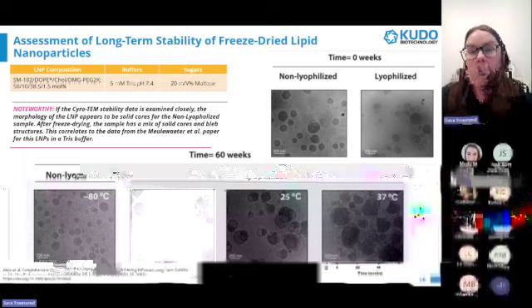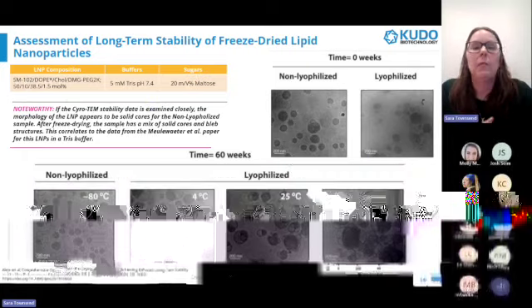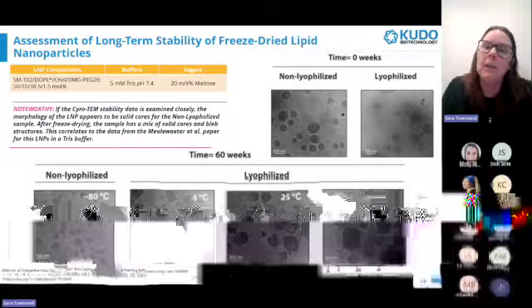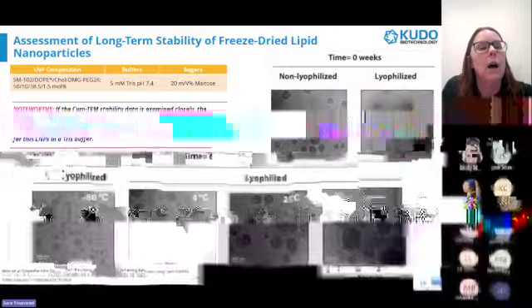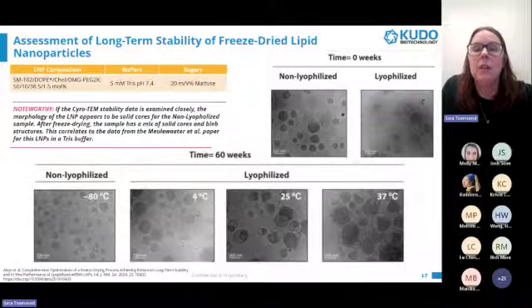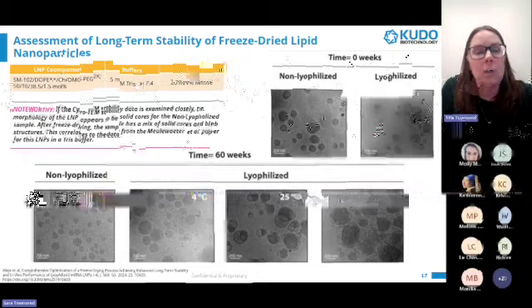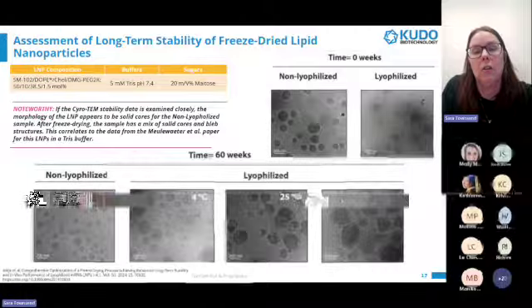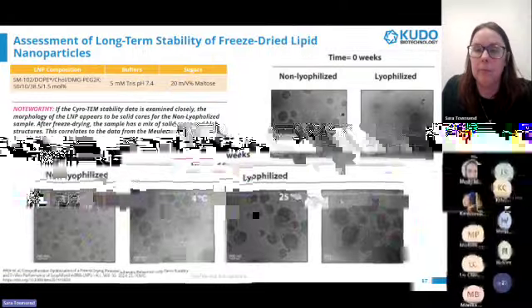Xu et al. also published on cryo-TEM. If we look carefully at the pictures, we can see a correlation between these results for Meulewater. The non-lyophilized appear to be solid. Here's the non-lyophilized. Again, they're using Tris. They have a completely different lipid, but their cores are very similar to Meulewater. After lyophilization, there are some bleb structures that come in, and over time it seems like there are more and more of these bleb structures. Definitely, and there's some aggregation here for the 7.